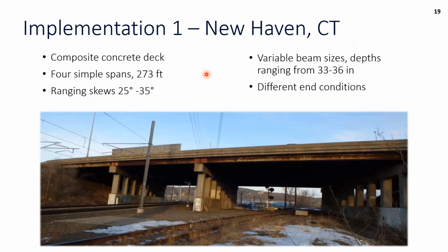So this is just another view from farther back. We had a composite concrete deck. One of the really unique parts about this bridge is we had variable beam sizes. The depth of the beams changed. We had different skews ranging from 25 to 35 degrees. We also had different end conditions. Some beams had bearing stiffeners and some did not.